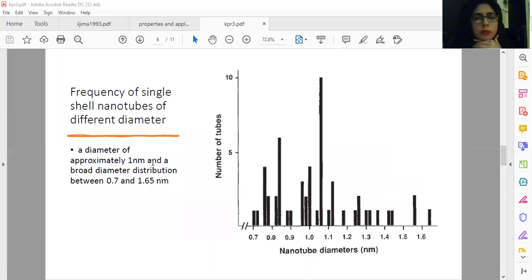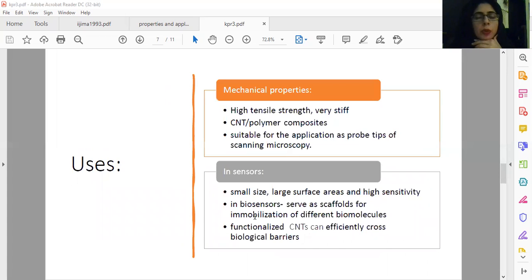In another image, they plotted a histogram to look at the frequency of single shell nanotubes with different diameters, and a diameter of approximately 1 nanometer was concluded, with a broad diameter distribution reported between 0.7 and 1.65 nanometers. So now we'll come to the many uses of carbon nanotubes. They've been reported to have a great deal of variety in terms of properties: mechanical properties, electrical properties, and optical properties. I'll be listing some of them in the upcoming slides.